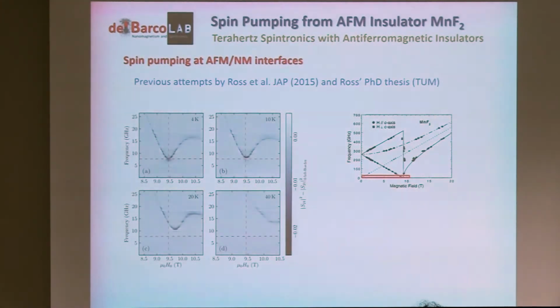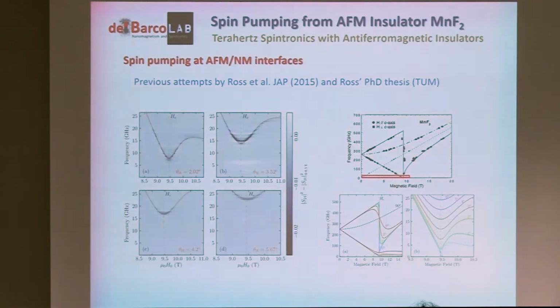They have looked at what happens, or how this evolves with temperature, or importantly for my experiments later, how this behaves with the orientation of the magnetic field with respect to the uniaxial anisotropy axis of the material. Some calculations tell you that as soon as you get a few degrees away from the easy axis, you won't be able to resolve the spin flop transition. This guy here will just move up, and eventually you won't see it. And this is what they observe here, right?